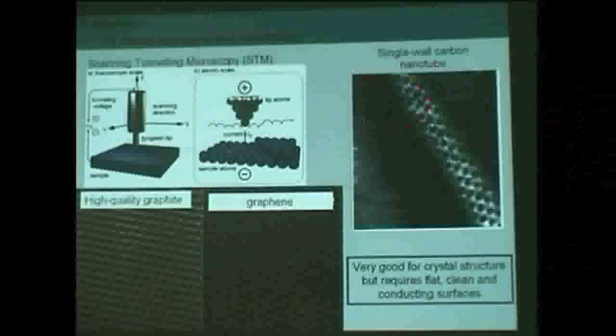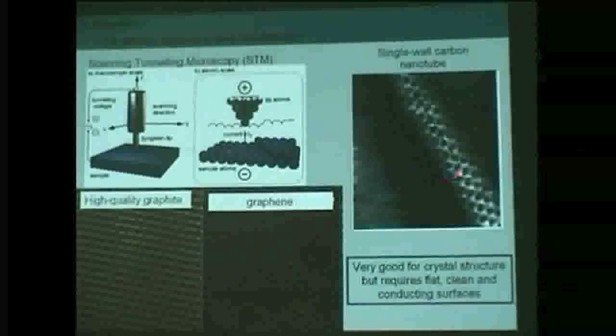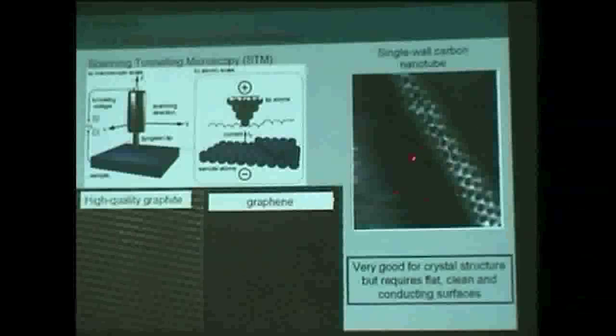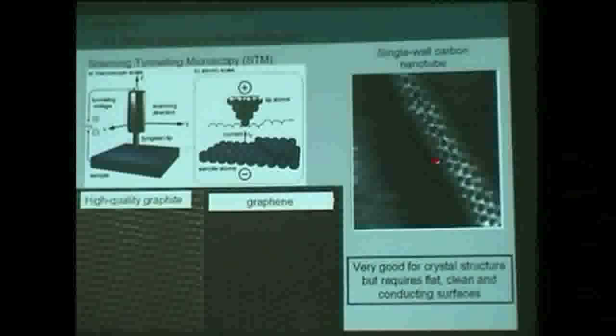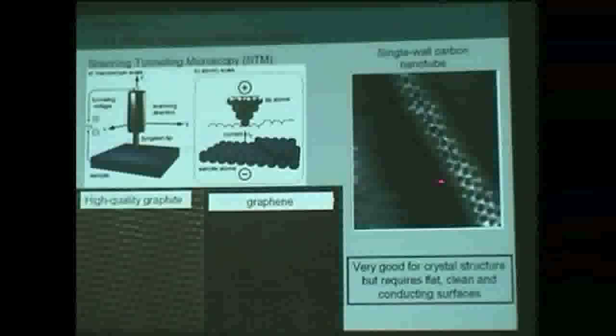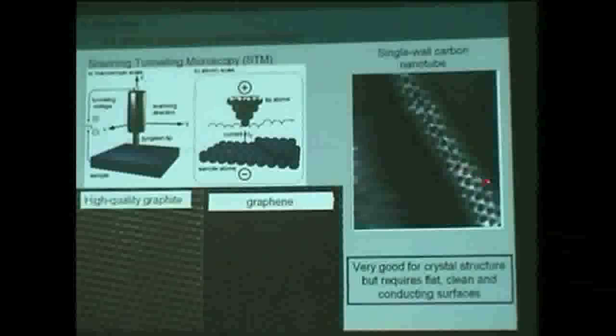If we apply that to the case of single-wall carbon nanotubes, we get this picture. We also find this hexagonal lattice like in graphene, but this time it is rolled, as you see here. Here is the tube, here is the substrate. We see the hexagons of carbon, and there is some chiral angle between the axis of the tube and the C-C bonds, which is theta here.